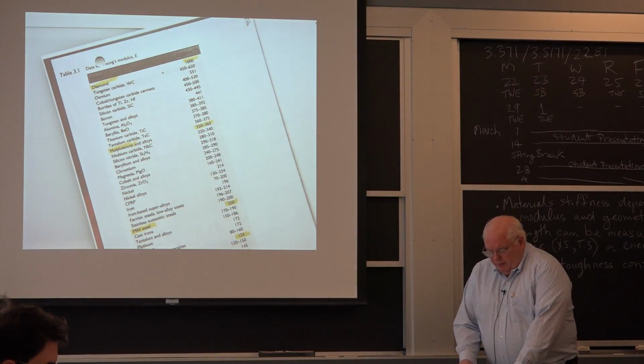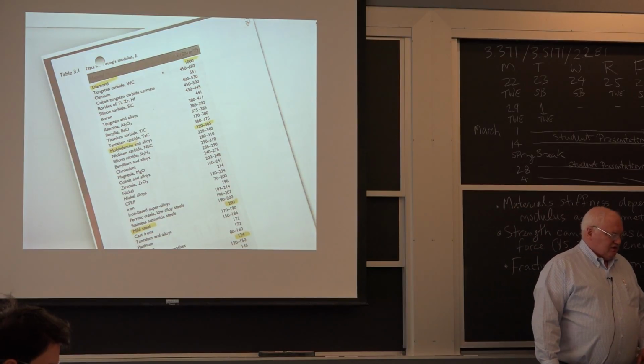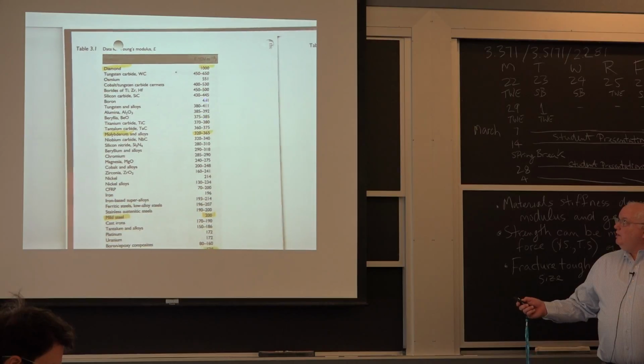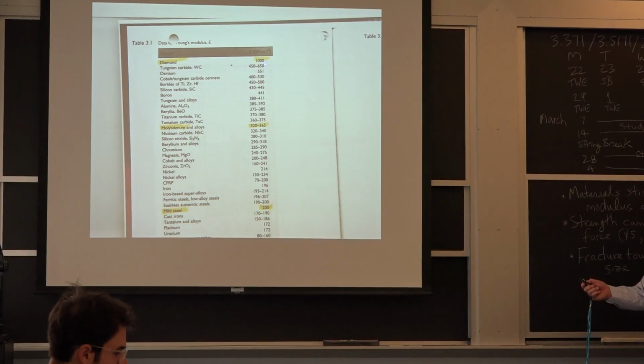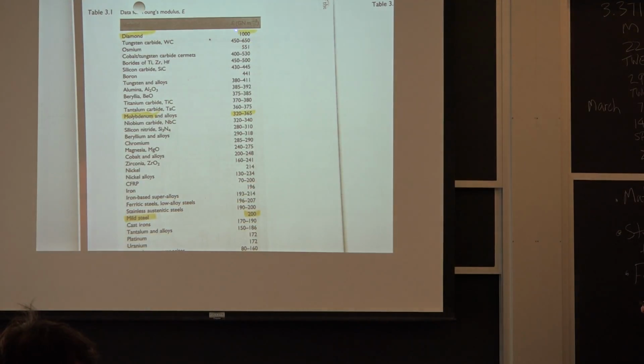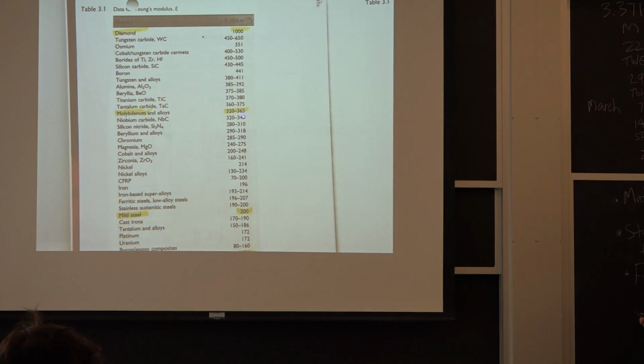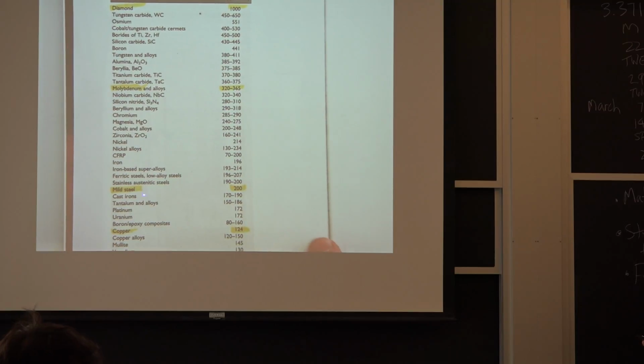You have to understand the difference in magnitude of these things, which is one of the reasons I kind of put it up. We talked about diamond being the highest modulus. In gigapascals, it's 1,000 gigapascals, tungsten carbide is 450 to 650, depending on how it's put together. Tungsten in its alloys as an element, 380 to 411, so about 400. Molybdenum is almost as high, so far as that goes. A mild steel is way down here at 200, 1/5 of diamond. But it's still pretty high compared to all the other things.